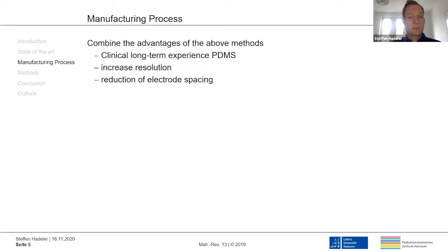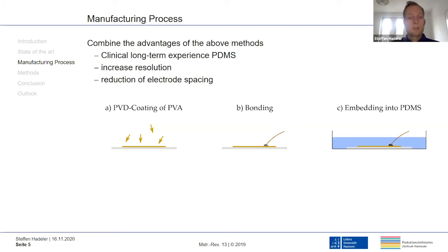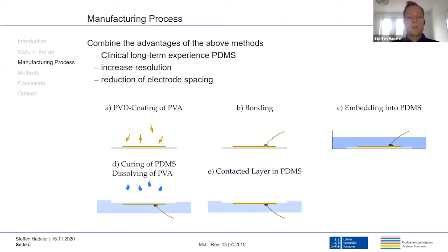In the following illustration, I show the manufacturing process schematically. First, a PVD coating is applied on a water-soluble transfer substrate of polyvinyl alcohol. Then the conductive structure is contacted for evaluation using conductive epoxy and wires, and after that it is embedded in PDMS of the type Sylgard 184. After curing the PDMS, the transfer substrate can be dissolved using only water, and the contacted conductive structure remains in the PDMS. Finally, certain areas can be isolated in the PDMS.